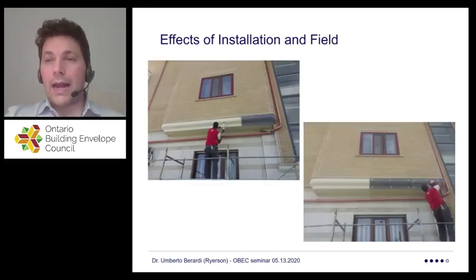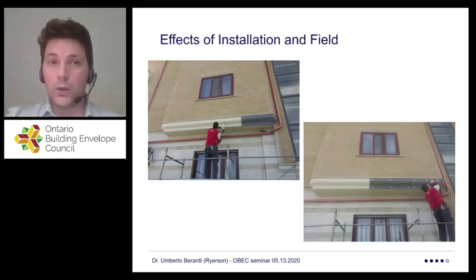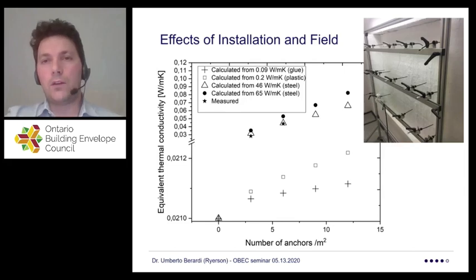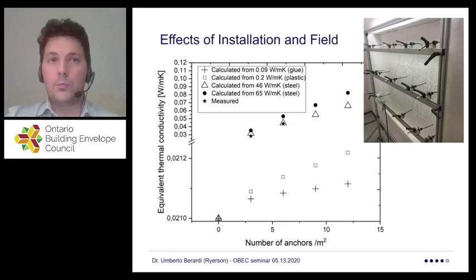And what can happen, for example, and this is another installation that we did with aerogel blankets, when we use the highest performing materials and we attach them to the wall with a glue, with different kinds of sealing, or with some kind of fastening on plastic. Now, I don't have time, but I want to give you a snapshot of the result of this investigation. What you can see here is an investigation done in a lab where we compared just putting glue, putting fastenings that were plastic, putting fastenings that were different kinds of steel. And so here you see the different kinds of markers.